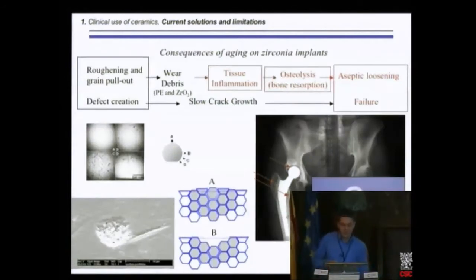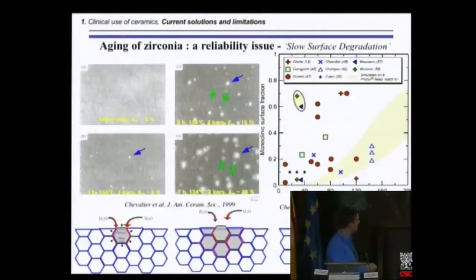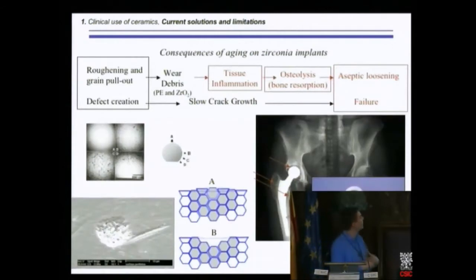What are the consequences of aging of zirconia? First, as we have surface uplift, because remember that phase transformation occurs by an increase of the cell of the zirconia, so an increase of the volume of the grain, there will be some surface uplift with time. We see it clearly here. This blank white zone is related to surface uplift at the surface. So if you're wearing against polyethylene, for example, you have a wear rate increase of the polyethylene due to this surface roughening of zirconia. That's the first point.